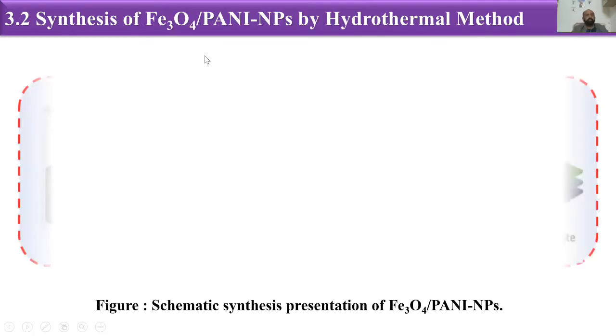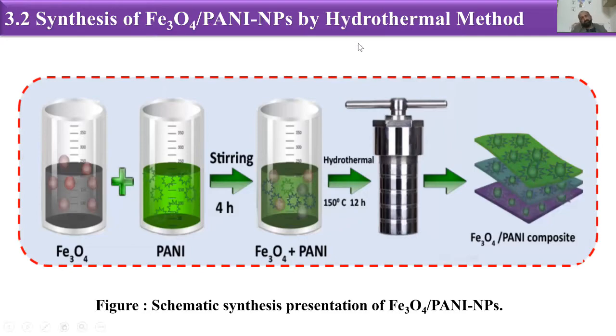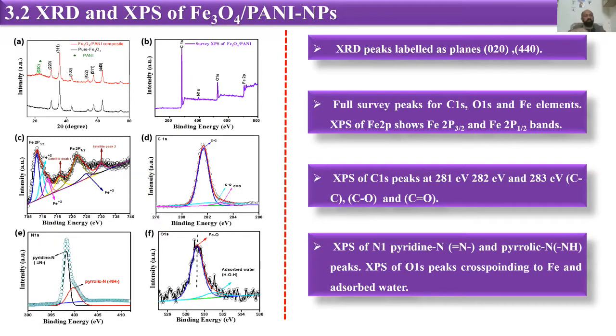Then next we have done our Fe3O4 Pani nanoparticles by the hydrothermal method. We have prepared Fe3O4 nanoparticles, and then we have synthesized them with the Pani material, and we have got the composite of these two materials by the hydrothermal method. And then we have done some of their characterization as well. Again, we have done the XRD and XPS of our Fe3O4 nanoparticles, and we have seen all the peaks which are related to the iron and Pani composite.